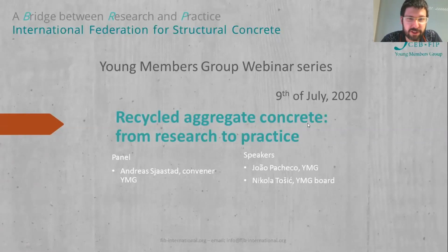There will be an effect, of course, in the tensile constitutive relation. As you saw first, you will have the lower tensile strength, but then another thing which you also saw, the lower fracture energy. So again, you're going to have a kind of weaker type of concrete, so a deterioration of the constitutive relation. But again, nothing out of the ordinary. It is going to be important for long-term effects. Of course, the creep, which is now going to come into effect even in the tension part, affecting the bonding of the fibers, especially if you're having synthetic fibers. So it's something to be careful about, but it's not still on a level that is advanced for any design recommendations.